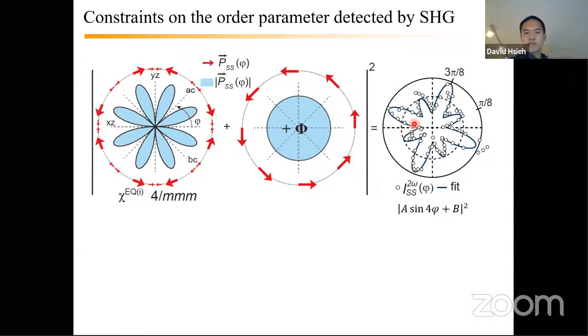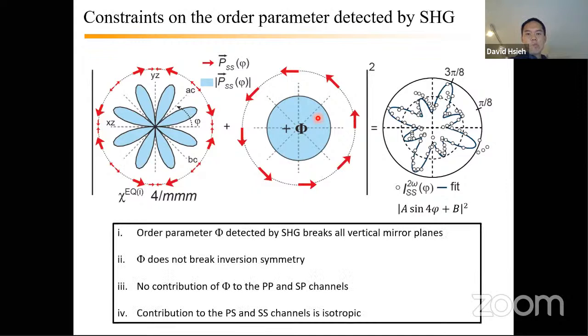We'll call that order parameter phi, and plus phi will be one of the two time reverse partners of that order. If you were to have minus phi, for example, then instead of big, small, it would be small, big, small, big. So what do we know about our observations? We know that this new order parameter phi, whatever it is, detected by SHG, breaks all the vertical mirror planes. It does not break inversion, since we see the signal go away in the SS channel at normal incidence. There's no contribution in the P out channels, and the contribution in the S out channels is isotropic,